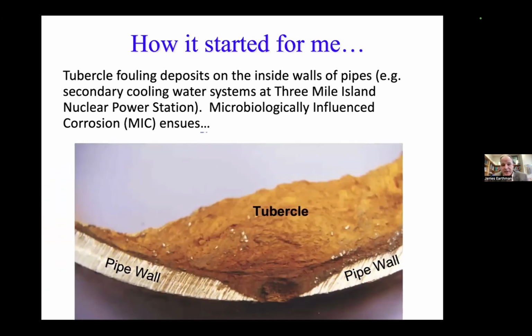And this is the problem that they eventually create: these tubercles get colonized by bacteria that can induce corrosion. The upper parts of the tubercle are typically colonized by aerobic bacteria. They consume the oxygen diffusing into the tubercle. And then at the bottom, there are typically anaerobic bacteria, like sulfate-reducing bacteria, that can thrive down there because there's very little oxygen. The sulfate-reducing bacteria create iron sulfide, and the iron for the iron sulfide comes from the pipe wall. And so, as you can see, you tend to get this localized corrosion. Eventually, the bacteria will eat through the pipe wall, and then you have a leak and you have to shut down the system. Very expensive.